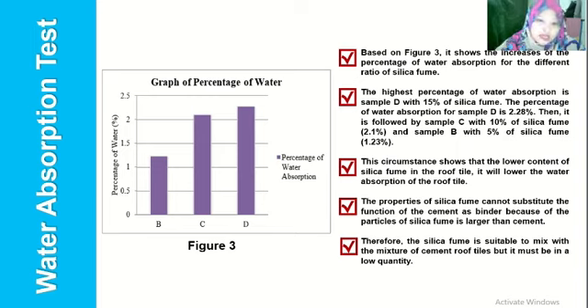Based on the figure as shown here, the percentage of water absorption increases with the different ratios of silica fume. The highest percentage of water absorption is sample D with 15% of silica fume. The percentage of water absorption for sample D is 2.28%. Then it is followed by sample C with 10% of silica fume, which is 2.1%, and sample B with 5% of silica fume, which is 1.23%.